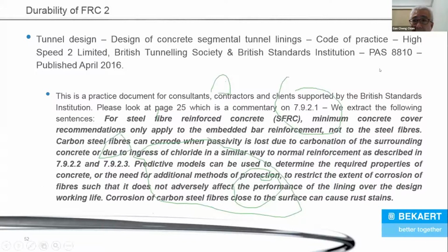And then this is published by the British Standards Institution. It's called PAS 8810. The title is Design of Concrete Segmental Tunnel Linings, Code of Practice, published also in April 2016. And here, if we look at page 25, for steel fiber reinforced concrete, minimum concrete cover recommendations only apply to the embedded bar reinforcement, not to the steel fiber. So we do not provide concrete cover for steel fibers. Steel fibers can corrode when passivity is lost due to carbonation of the surrounding concrete or due to ingress of chloride in a similar way to normal reinforcement.